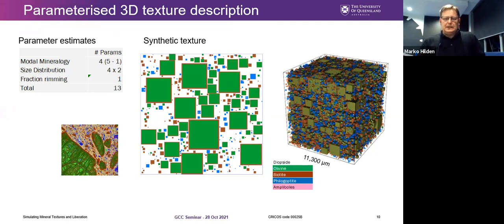And if you look at the image, you can see that the biotite forms a halo or rim around the olivine minerals. So it appears that we can add a parameter that specifies the proportion of biotite that appears in that form as well. We don't need to define the grain size distribution for that because it's just wrapped around the olivine. So 13 parameters describes this model of the texture and gives a 3D model, and you can see the 2D slice there as well, which is a representation of the measured texture.